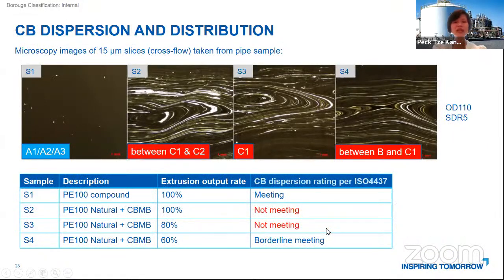As I mentioned, the ISO standards do require the carbon black to have a good distribution. The distribution is actually like a protection against the UV. In the case of sample 1, the distribution is very nice. You don't really see any smearing white area. But samples 2, 3, and 4 are actually quite bad. It's almost like the Milky Way or the galaxy, where you see this white area with no carbon black.